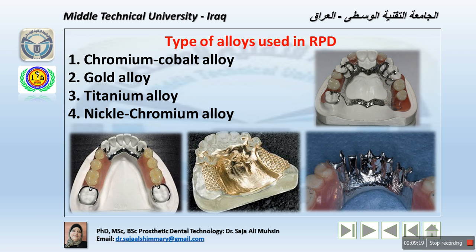And the molybdenum, which is between 0 to 7%, affects the hardness; it refines the grain structure, that means giving the alloy a fine texture. And the iron between 0 to 5% affects the hardness as well, and the carbon up to 0.4%. The small amount may have a pronounced effect on the strength. You know that the carbon affects the hardness and ductility. Carbon forms carbides with the metallic constituents, which is an important factor in strengthening the alloy. However, excess carbon increases brittleness of the material.